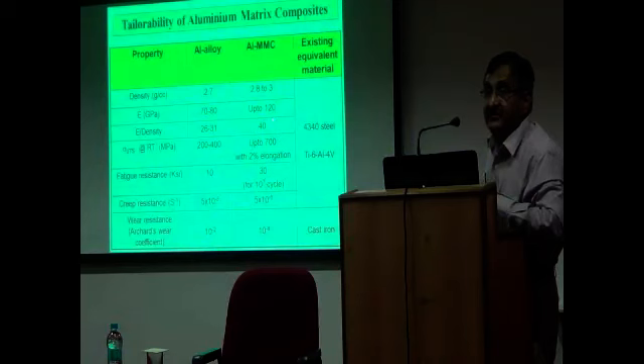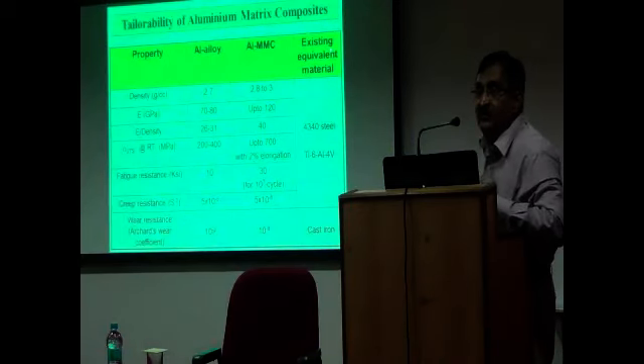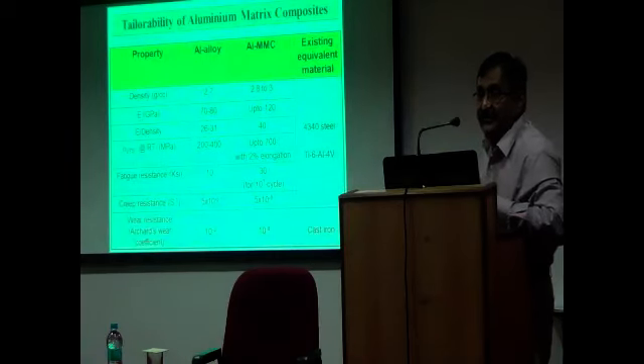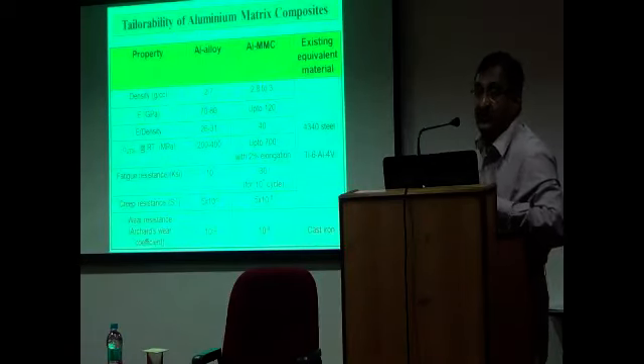It means that steel, which has a density of more than 6, you can achieve the properties of steel at up to 1/3 the density. And titanium, which is a very expensive material, you can achieve those properties by compositing aluminum with any of those reinforcements.